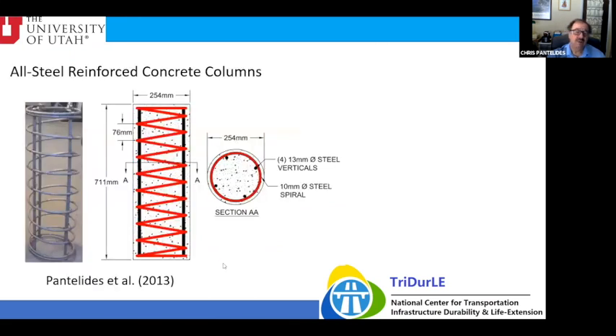So here it shows you the first study, the initial study we did for corrosion. This is the study that Mike Gibbons was involved in. You can see these columns are 254 millimeters diameter, 711 millimeters tall, and this is all steel. It's all carbon steel reinforced. You can see four 13 millimeter steel verticals and 10 millimeter steel spiral at 76 millimeter pitch.